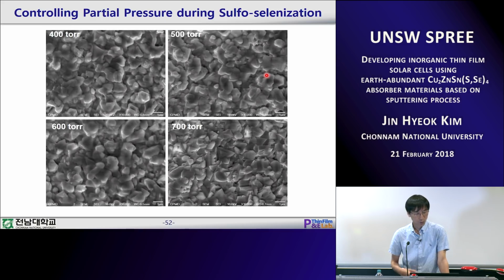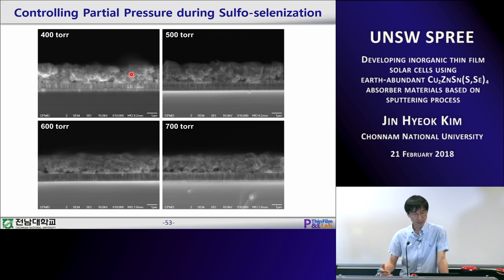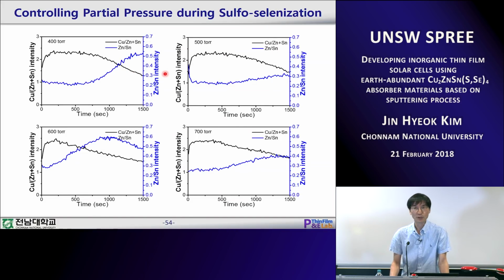We changed the outside pressure from 400 to 700 torr, and we don't see that much difference in the microstructure. In the cross-sectional images, we also don't see much difference in the microstructure. But if we look at the composition ratio, we can see that in the 500 torr sample, the zinc over tin ratio is relatively uniform throughout the whole absorber layer compared to these three samples. We want to keep the composition as uniform as we can in the absorber layer because that is important.